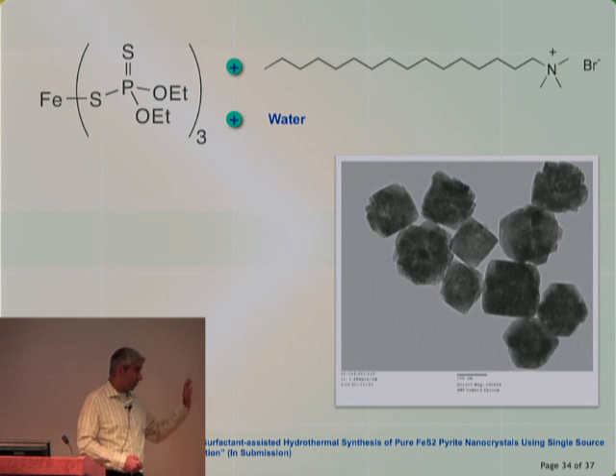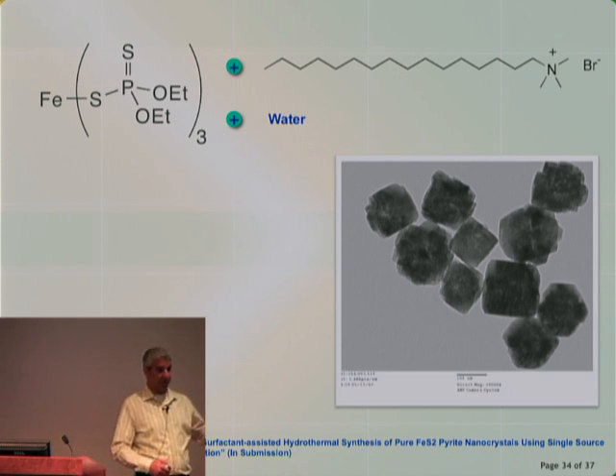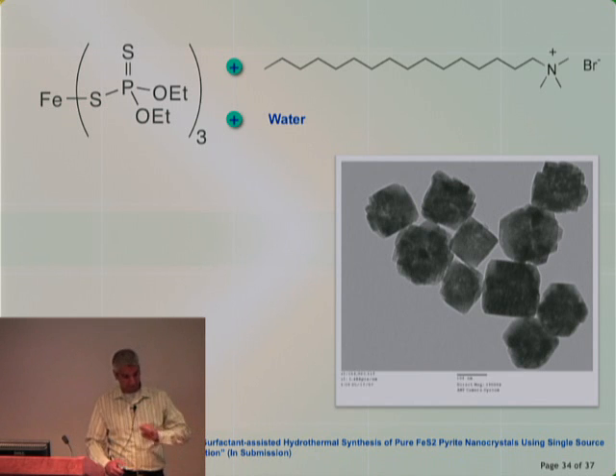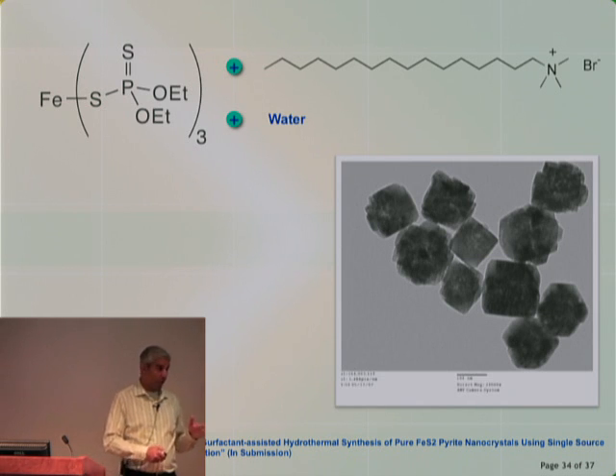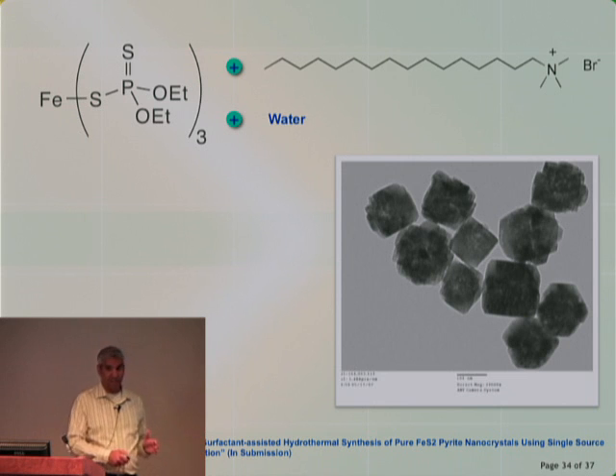And these iron sulfide blocks are very large. Remember the copper sulfide was about 5 nanometers, so I had this very nice material I could just spin down on substrate. These are much bigger. These are 200 to 500 nanometers. So, one of the issues I've run into in making devices is how do we actually deposit these on a substrate, because they don't pack quite as nice as those small particles.